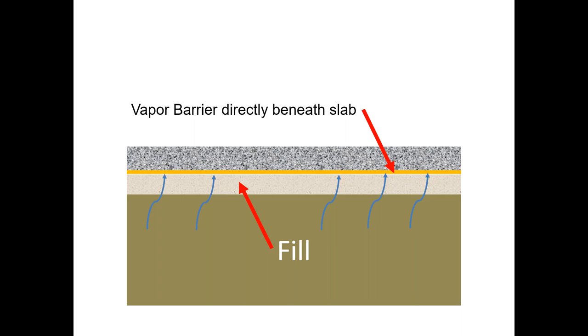So the thought there on curling, and the most recent studies are showing, is that the vapor barrier actually is not creating excessive curling, and if anything it's actually reducing the curling. Now that's up for debate. It has been up for debate for a very long time, and I tend to go with the way that the Institute is going now, but I wouldn't argue too hard with somebody about it.